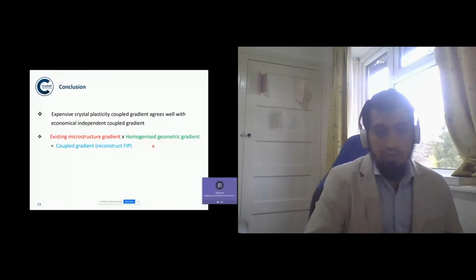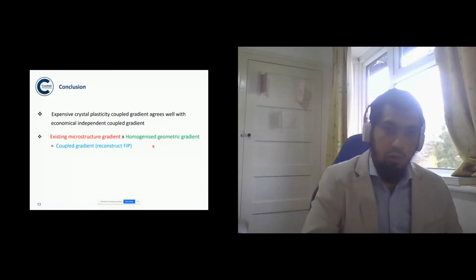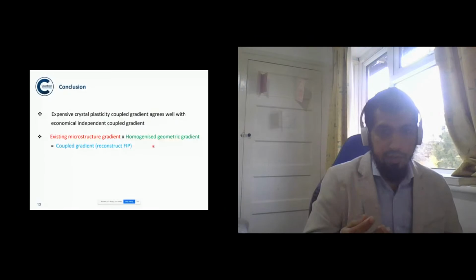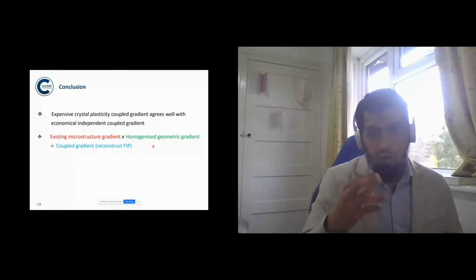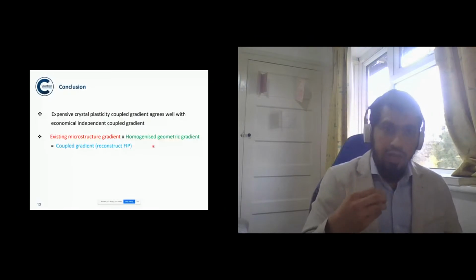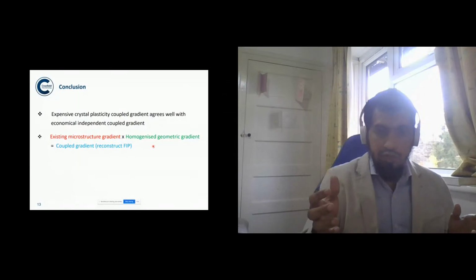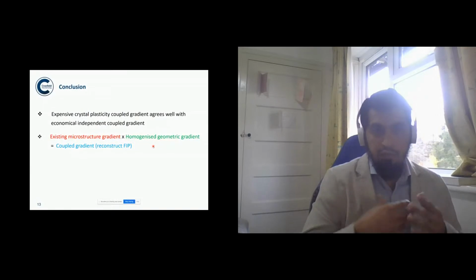so for example, in this case, we have a notch as a geometric gradient, but in the real fatigue problem, we have several other geometric gradients, like we may have a circular hole or other things. For that case, what we need to do is independently quantify the effect of that geometric gradient. Since the microstructure gradient is not changing, we can couple that independent gradient effect and we can make a fatigue prognosis with the less computationally intensive simulation.